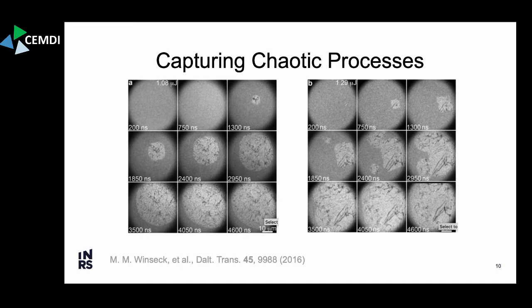The thing is that this is a rather chaotic process. You can see that by just changing the laser energy by a little bit, you get very different microstructures of these materials. It goes from a single nucleation point into multiple nucleation points, and they grow in together and have different ending defects and ending microstructures in the end.